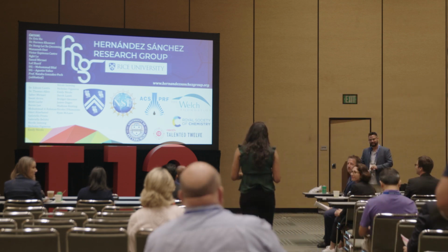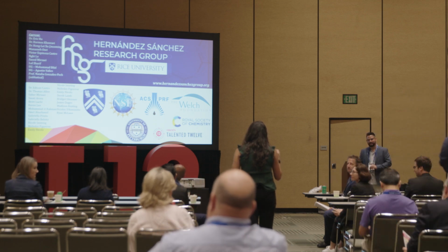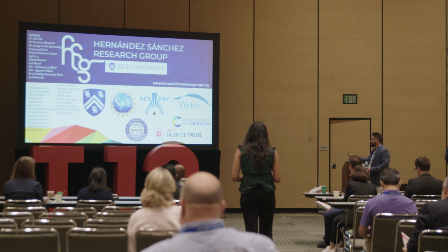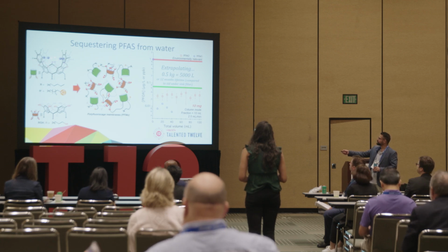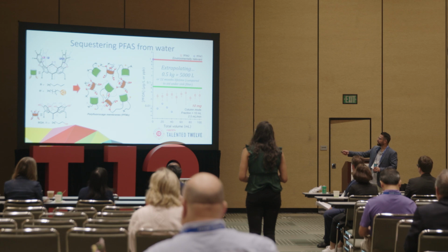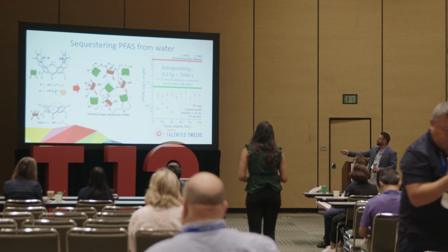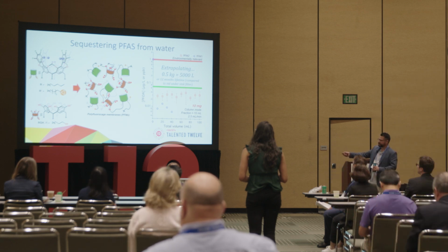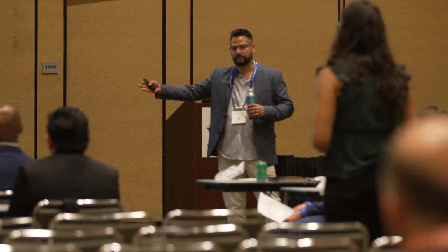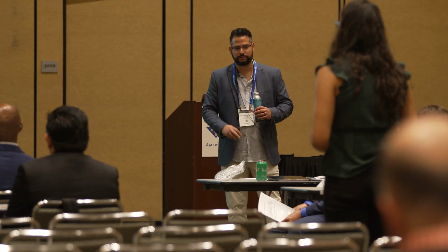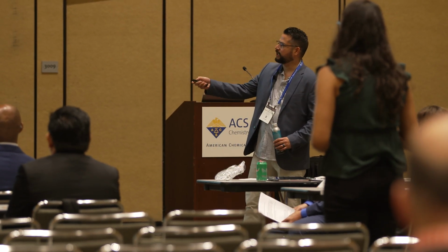So I may have missed it, but for the PFAS sequestration, what are the interactions that allow for that sequestration? Right. So essentially, this molecule is the active ingredient, if you wish. This molecule is binding the anion part by having this CH bond heavily polarized. In the polymers that we've made, we now have data showing that it's the anionic part being sequestered in that pocket, and also any CF3 moieties that are lying around. So in a PFAS, the terminal part, the last carbon, which is the methyl, the CF3, can bind also in that pocket. So we have a double effect from these particular anion binders.